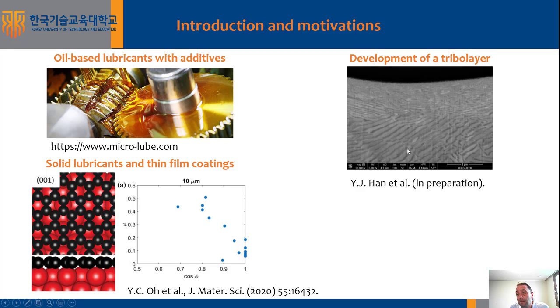Another promising solution to reduce friction and limit and retard wear of metallic surfaces is the development of tribo layers. So we are currently working on the formation of such tribo layers on a eutectic alloy, where we find that upon scratching on such a microstructure, we first deform the lamellar eutectic structure, in that case of a silver copper eutectic alloy, and ultimately refine the lamellar structure until we in fact may mix copper and silver together with some oxygen to form a very nanocrystalline or maybe even amorphous tribo layer.